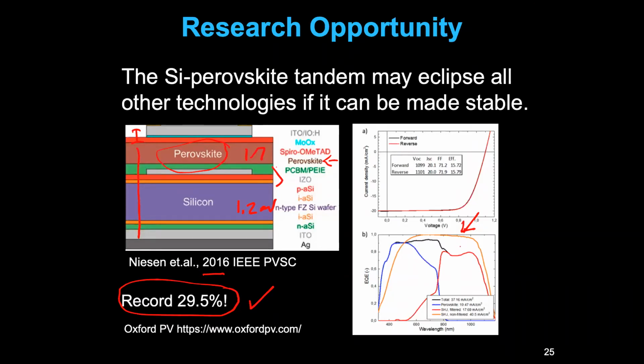That's the trouble with any multi-junction: you have to have a stable bottom cell. That's why the silicon perovskite tandem is so attractive, because the silicon is not going to go anywhere. Therefore, I have planned to make the bottom perovskite layer by solution processing and the top perovskite layer by vacuum deposition or something. But vacuum deposited perovskite solar cells still have very low efficiency. So that is a problem. Okay, thank you very much. Good luck. It's a good research problem. Yeah, that's right.